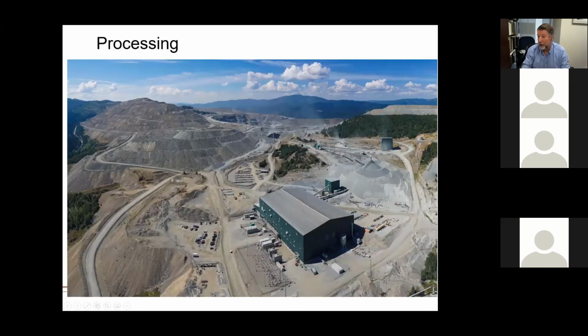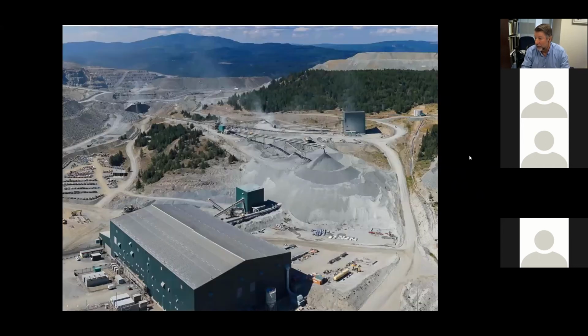If we get into processing, this is a view of the mill building, looking at the pit areas over here, waste storage areas here, and we'll just take a close-up look here to describe some of the features in there. Primary crusher sits over here, relatively close to the pits. Crushed ore is conveyed up to here. In 2014, a secondary crusher was added because the hardness was preventing full production getting through the SAG mill. And so this was added here, and the conveyor system is divided so that